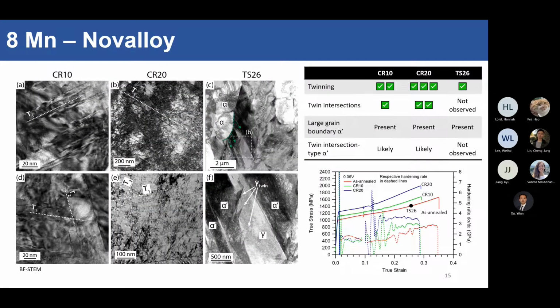Okay, so to answer these questions, we dive into TEM. In the cold roll 10 sample, you can see we've got some twins going on here, and then we also have some twin intersections going on here, but there's no martensite at these twin intersections. In the cold roll 20 sample, we got more twins with higher density of twins, which is nice, and consequently a higher density of twin intersections. But again, no martensite at the twin intersections. In the TS26 sample, so this is pure uniaxial tensile, you will notice that there are very few twins. Where did the twins go? We only have 3 very lonely twins here, and you can see this big martensite lump just absolutely punching its way through.